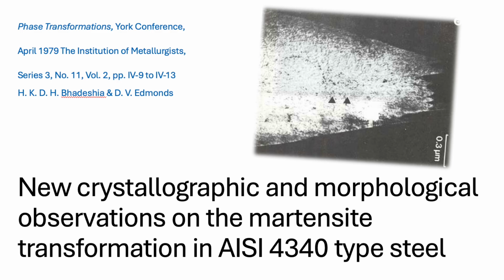This allowed them to actually see the structures and map out the relationships between the laths and plates. What did they find visually? Well, first, they confirmed the microstructure is a mix of lath and plate martensite, often partially developed. But the really crucial finding, based on how these structures were arranged, was that the lath packet really is the fundamental transformation unit, not the individual lath.